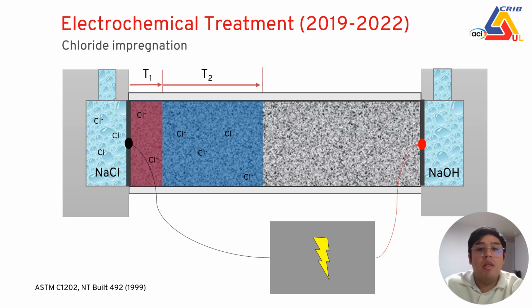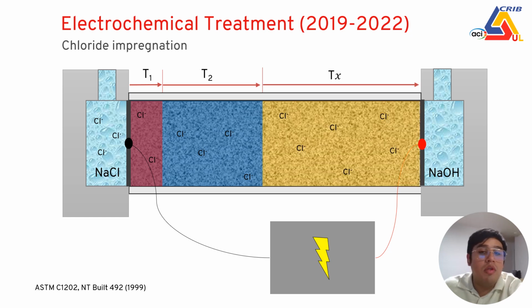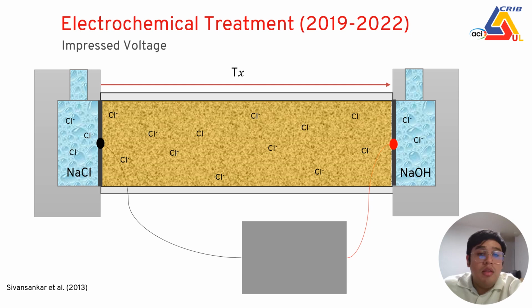This chloride little by little will migrate along the whole length of the concrete specimen until it reaches the other part of the solution. But it's really important to say that we need to control different parameters to avoid other attacks and so that they cannot be involved in the damage of the sulfide-bearing aggregates. The next step is to maintain this current for a long period of time to improve the oxidation reaction of the sulfide-bearing aggregates. This part we call the impressed voltage test.